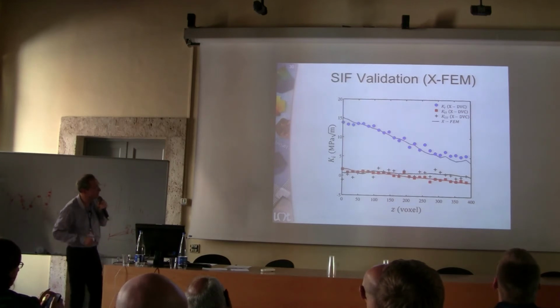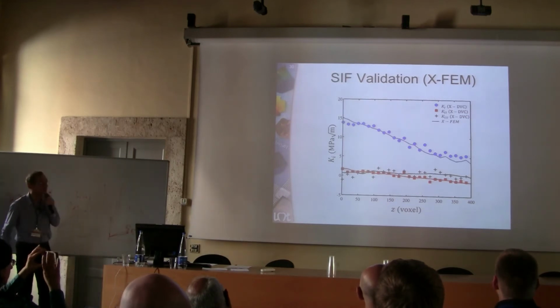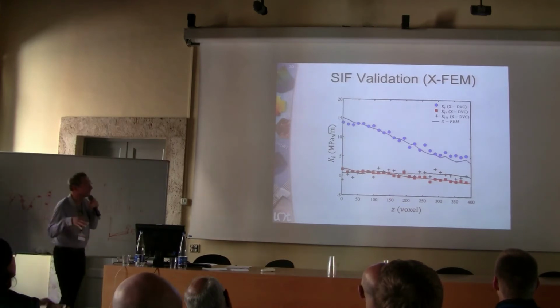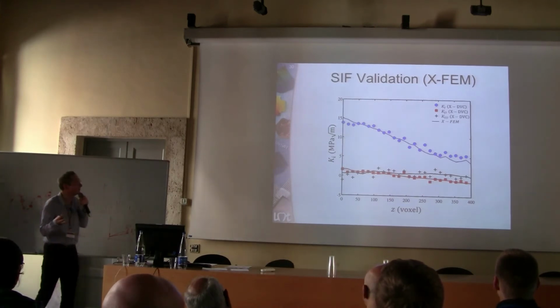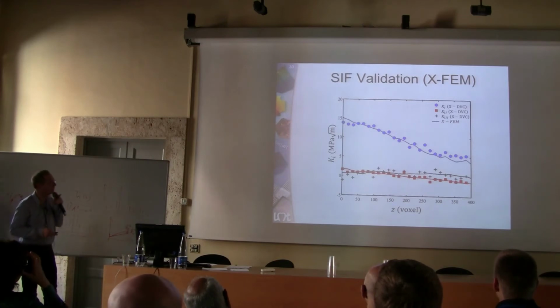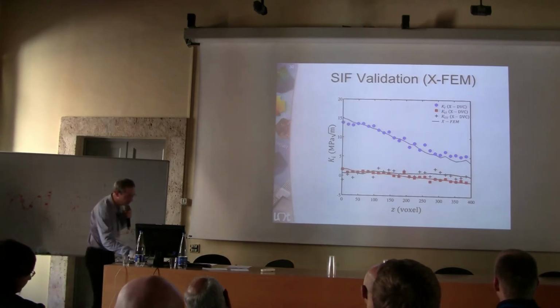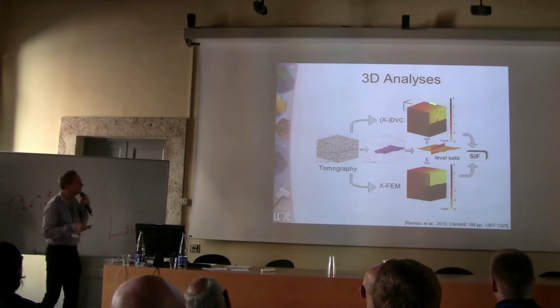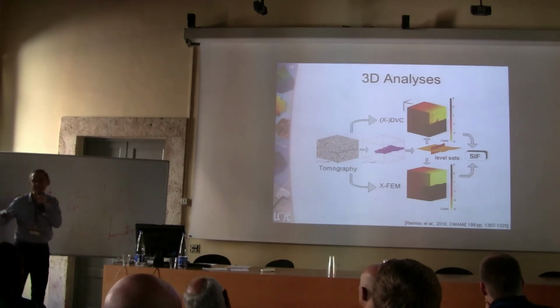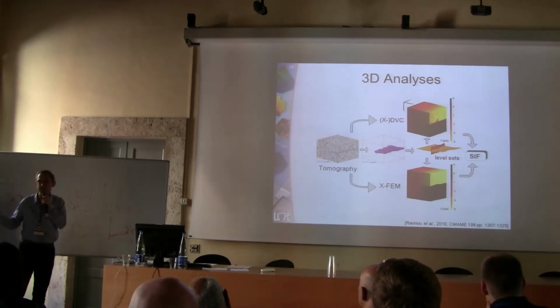And the symbols here are experimental evaluations. What you see is that there is a very good agreement that allows us to say that we validated these XFEM simulations. Please note that had we just prescribed uniform boundary conditions as you would expect from a perfect experiment...